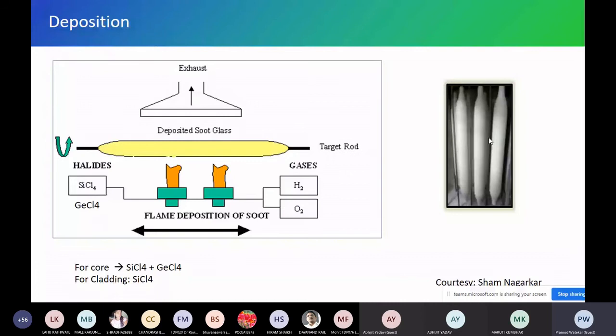Now OVD is a two-step process. It's not a single step. For example, we make the core first, then we make the cladding over that core. So it is two-step. Okay? We send SiCl4, for example, to the burner. Remember, we are sending it through the burner, not from here and there. In MCVD, we send it into the tube. Here we are not sending into the tube because there is no tube at all. So we send this material through the burner. So burning plus reaction has to take place. That is very important.